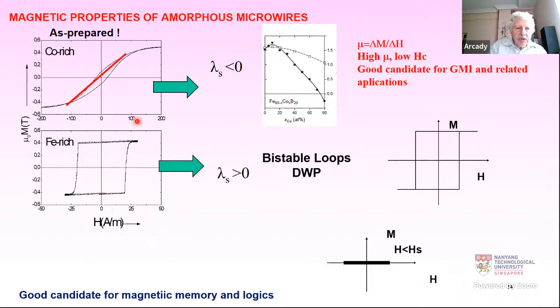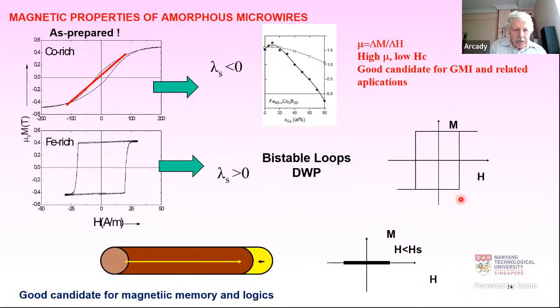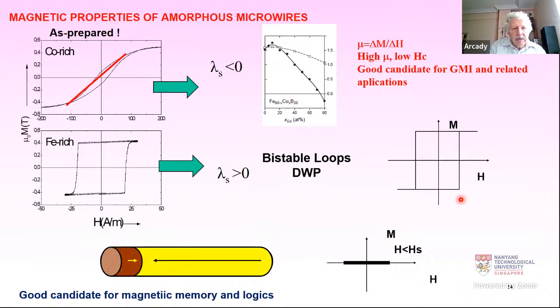If the composition has positive magnetostriction, we can have the so-called bistable hysteresis loop. Bistable is because below some critical field, we don't have even a hysteresis loop, and then this square hysteresis loop abruptly appears. And the magnetization can turn to positive or negative magnetization direction in two directions. And in this sense, our samples are magnetically very stable. This is because once we apply the reversal magnetic field, there is fast domain wall propagation, as you can see in this picture. And this is the origin of this perfectly squared hysteresis loop.